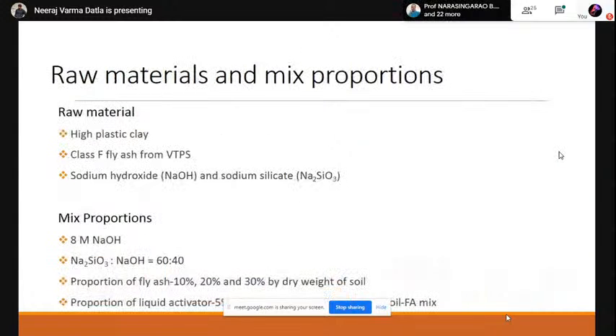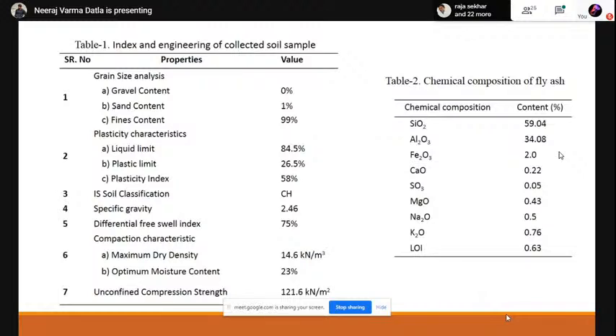Here, the raw materials used are high plastic clay collected from Guntur and class F fly ash from Vijayawada, and the alkaline solutions are sodium hydroxide and sodium silicate. The mix proportions are 8 molar NaOH solution, with a sodium hydroxide to sodium silicate mix ratio of 40:60, and fly ash is varied by 10, 20, and 30% by dry weight of soil, and the proportion of liquid activator is 5, 10, and 15% with respect to the soil fly ash mix.